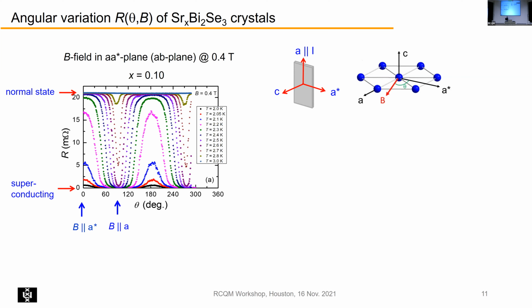So we did the experiment. We put a small field on the sample, 0.4 Tesla. Then we change the temperature, and we rotate the sample. Here is the field along A star. Here is superconductivity, here is the normal state. Then we change the temperature. For instance, if you sit at an intermediate temperature, you see here you're almost normal, this pink curve, and then it goes down and up again. So here we are completely superconducting. It means for this direction the upper critical field is large, and for this it is small.